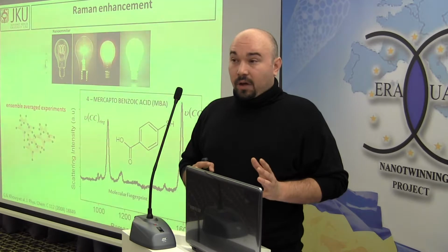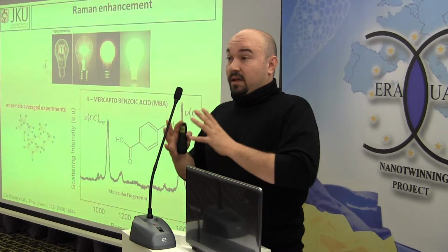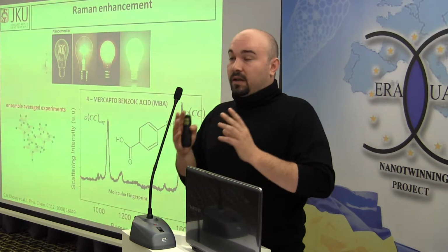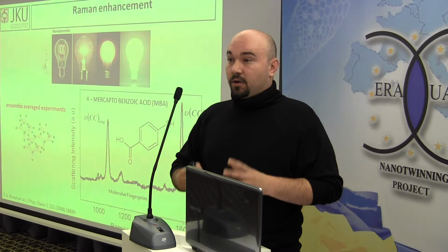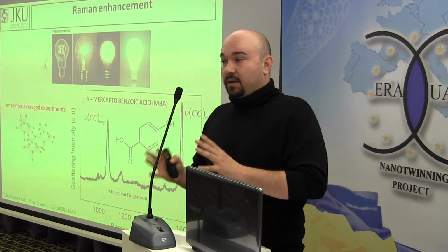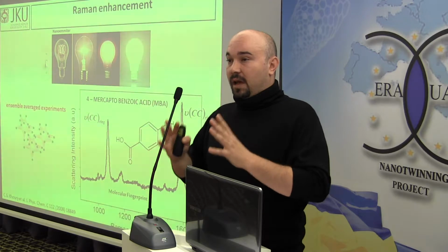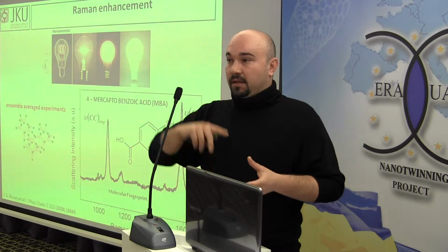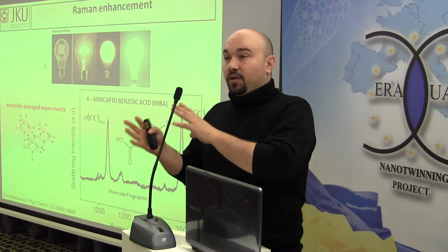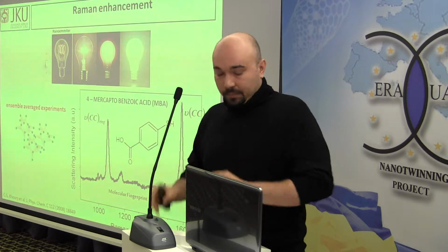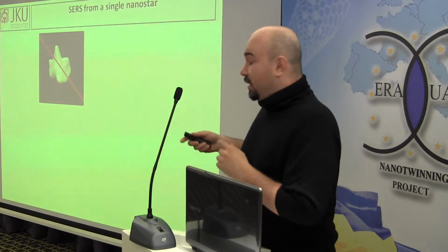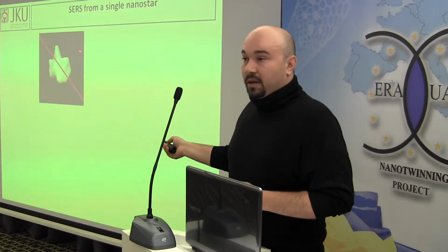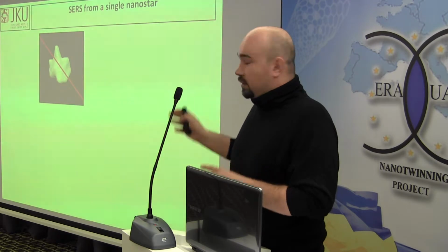So, in order to understand exactly where the Raman signals are coming from, we made optical measurements, and afterwards we did a TEM tomography of the nanoparticle in order to get its exact shape. This exact shape we put in a discrete dipole approximation calculation, and, taking into account the substrate and the molecule layer, we calculated the region of the highest field enhancement contributing to the Raman. So here you see our reconstructed nanostar. It's a 3D reconstruction. Our nanoparticle looks in this way.